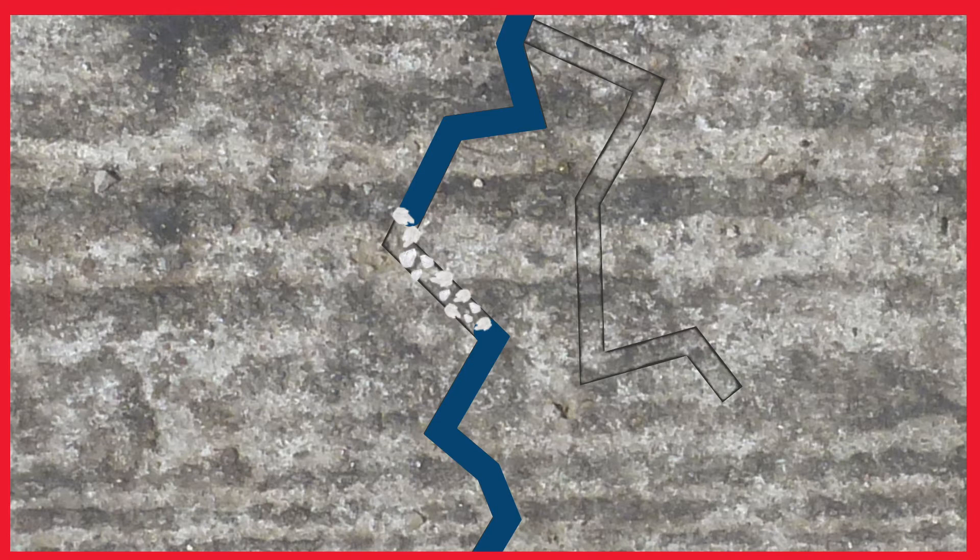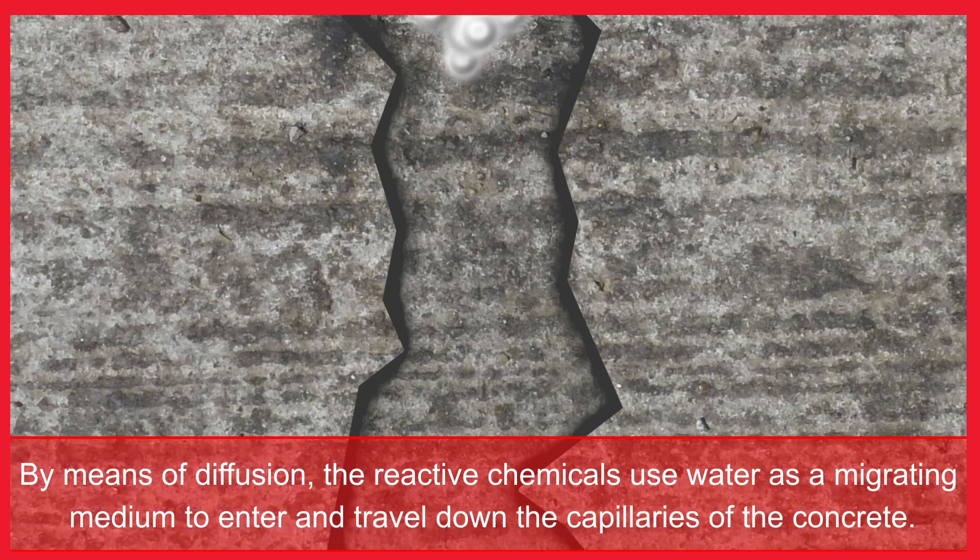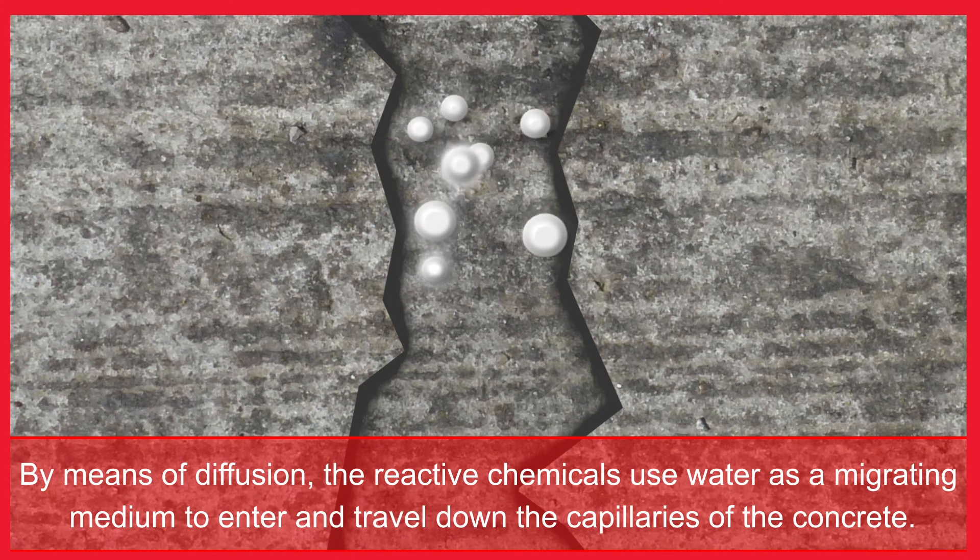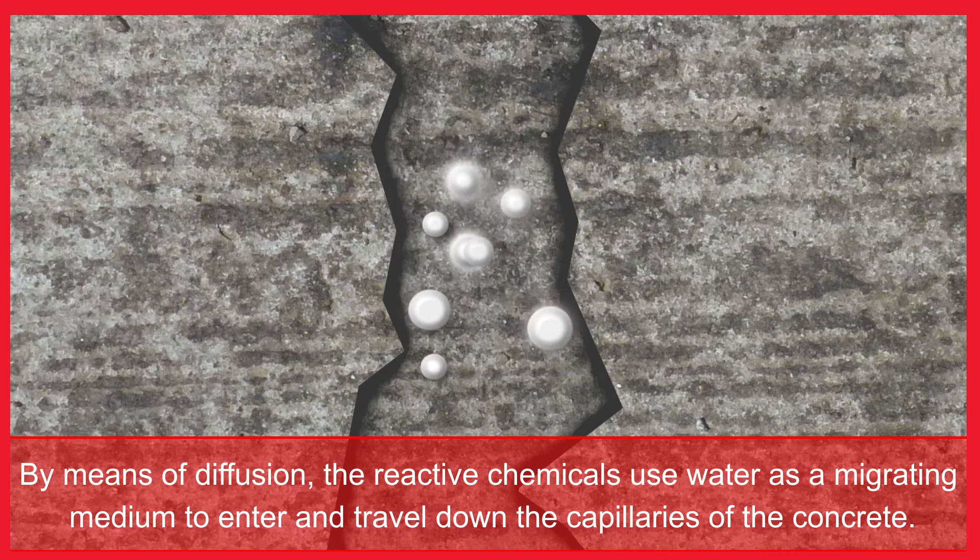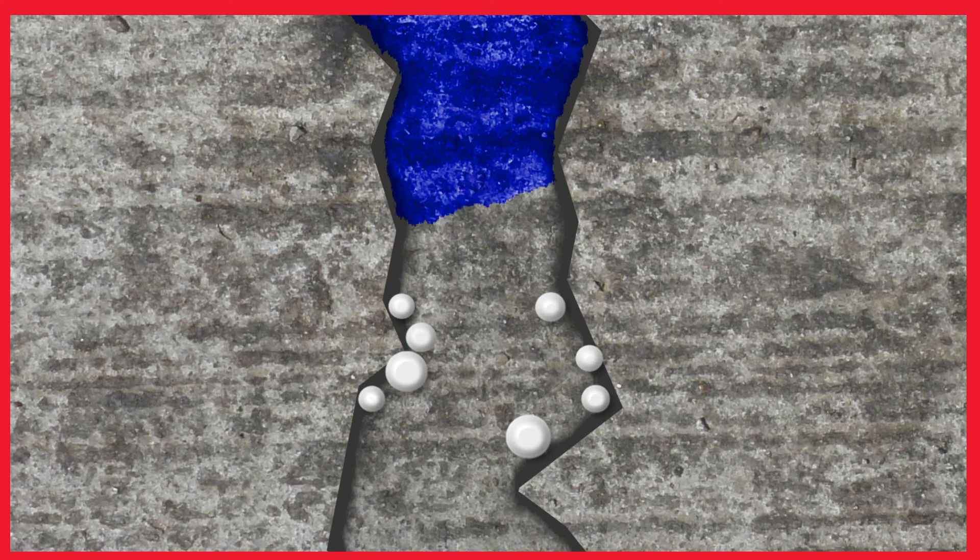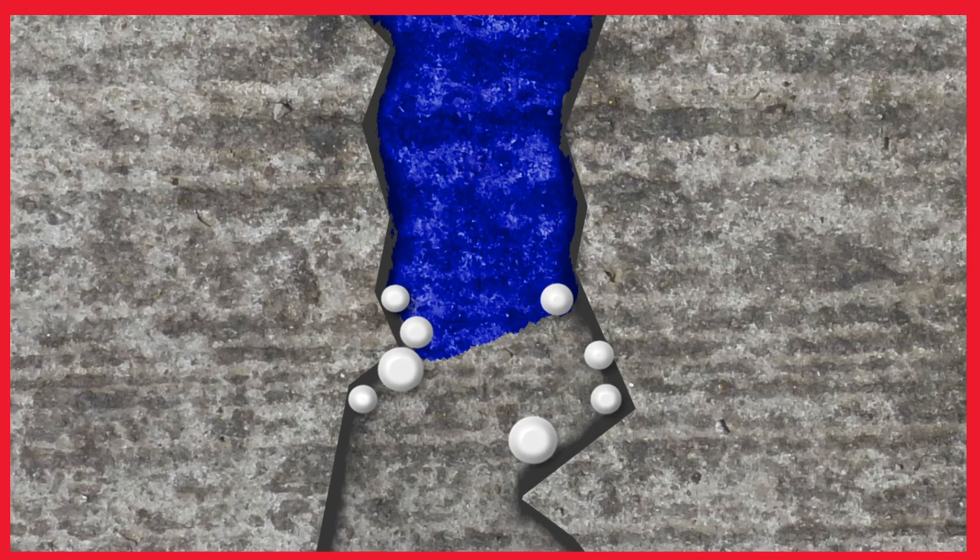The concrete itself becomes the water barrier. By means of diffusion, the reactive chemicals use water as a migrating medium to enter and travel down the capillaries of the concrete. This process precipitates a chemical reaction with any water ingress and free lime that is present in the concrete.